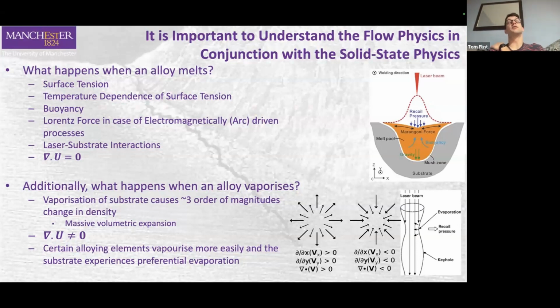That's all very well and good if you've got fluids that are behaving in that manner. But actually, what tends to happen is people use that simplification for fluids that aren't behaving in that manner. So the systems that we're interested in particularly are where you have quite a lot of vaporization. So if you apply, like I say, a very high energy density laser beam or electric arc, you actually vaporize the metal. So you get a much bigger volume of vapor produced relative to the amount of liquid that was vaporized. So you can't then describe that as being incompressible.